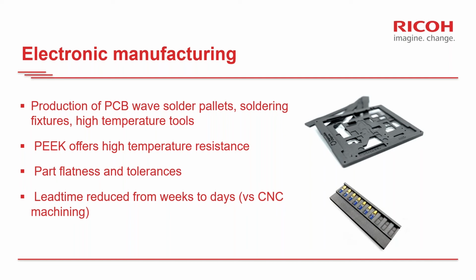And really, one of the benefits of the technology is that it enables you to produce large and very flat parts with no warping, which is quite challenging with a material like PEEK, and also to keep the tolerances required by this type of application. Also, thanks to the speed of the process, the lead time could be reduced from several weeks to, generally, 1 week to 10 days. And as there are no setup or tooling costs, it is also a very good solution for bespoke or low volume fixtures.